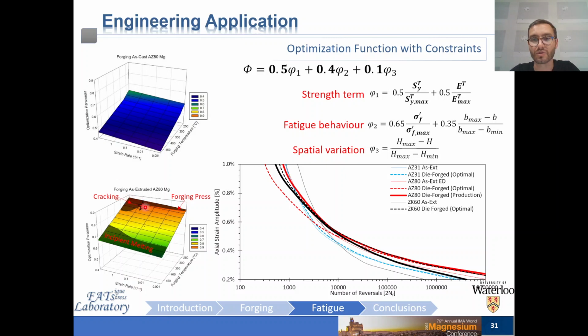Obviously, this optimum condition will shift here on the surface plot to obtain the next highest value once you impose those constraints. Furthermore, although not very significant in AZ80 magnesium, the cost difference between the cast and extruded forms that you might start with prior to forging, so the base material that you're starting with, might make another option seem more attractive if cost saving can justify the degradation of performance. So as we previously discussed in detail, going to a cast alloy to start with, you'll end up with inferior properties, but if the cost associated with that might be justified, then that's a decision that needs to get made from the design standpoint.